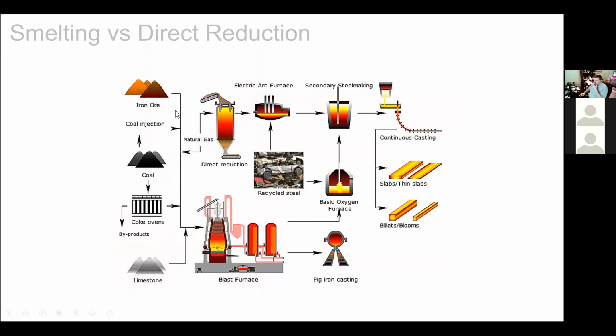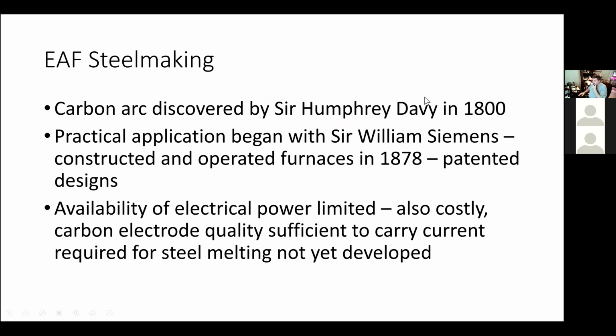Now, the main difference when you look at direct reduction, you look at the blast furnace, a lot of the materials that are used are very similar. We're using iron ore pellets. We use a higher grade of iron ore pellet for direct reduction because what we're doing is taking the iron ore and converting it to metallic iron without melting it. So we're doing it while it's still a solid. And we do that by reforming natural gas to produce CO and hydrogen. And that penetrates into the pores of the pellet and removes the oxygen. So it tends to be a cleaner process. And so a lot of people who have blast furnaces are looking at maybe in the future replacing them with direct reduction. And I've got a few slides that I'll show you in a minute.